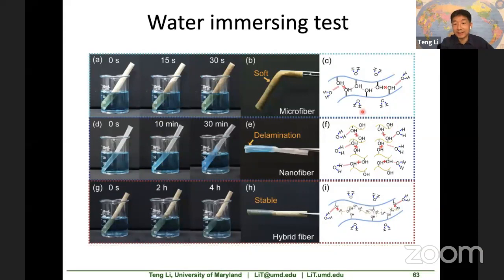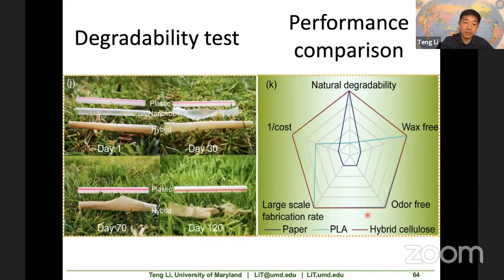Okay, this can be explained by the mechanics design we are trying to incorporate here. For the pure microfiber one, the water can wick along, and the capillary effect along these voids causes the dissociation of the hydrogen bond. So that's why it fails in a short time. For the pure cellulose one, the water attack will cause the dissociation of hydrogen bonds, so that causes the delamination. However, with this hybrid design, even though some of the hydrogen bonds are dissociated at these locations, because of this long microfiber, it protects most of the hydrogen bonds in between the nanofibers and they remain intact. So this leads to better water stability.